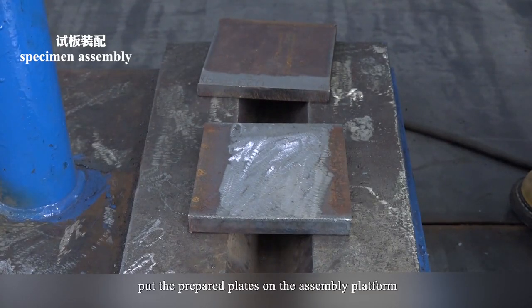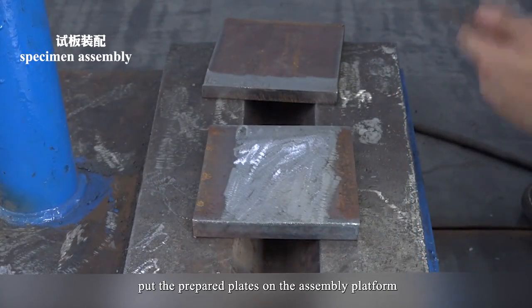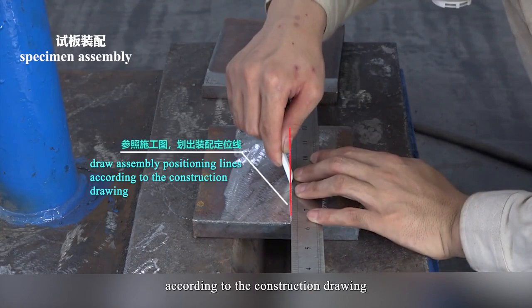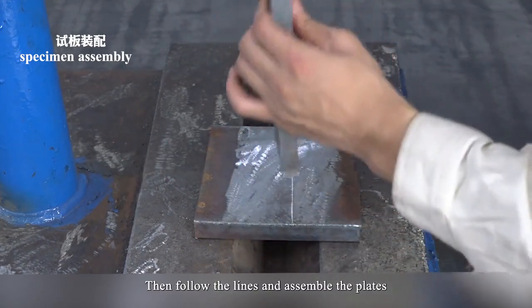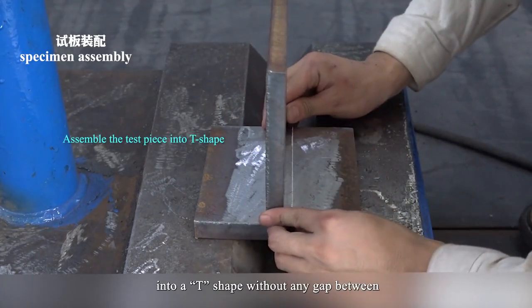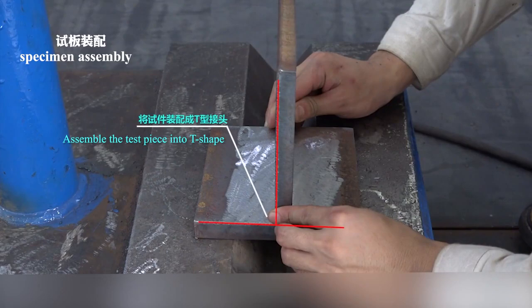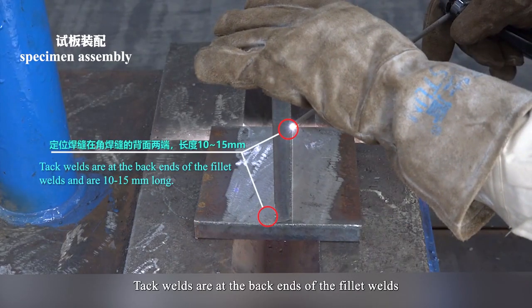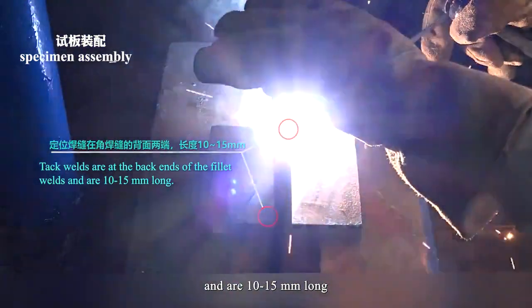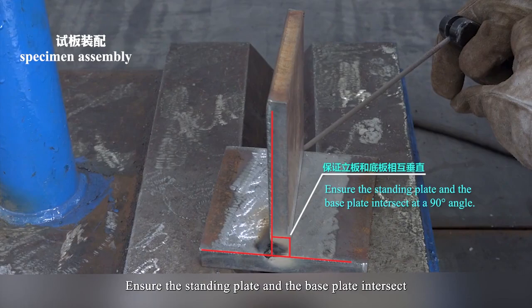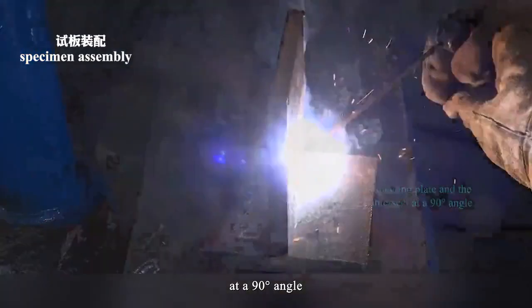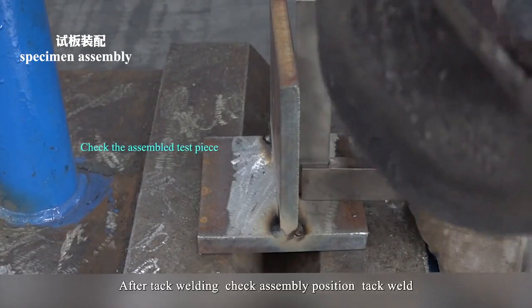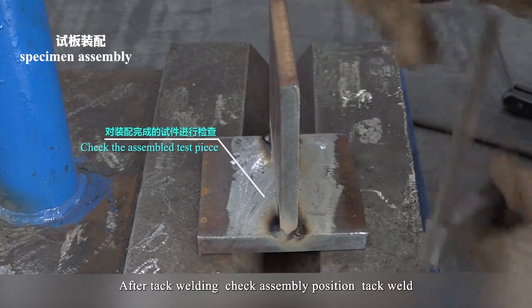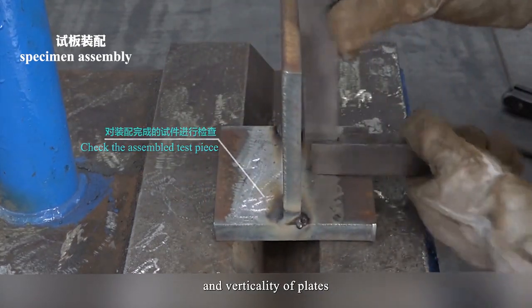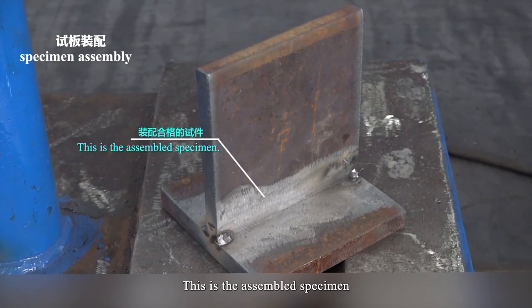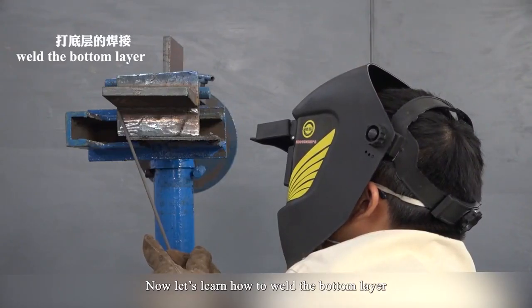First, pairing. Put the prepared plates on the assembling platform and draw assembling position lines according to the construction drawing. Then follow the lines and assemble the plates into a T shape without any gap between. Tack welds are at the back ends of the fillet welds and are 10 to 15 mm long. Ensure the standing plate and the base plate intersect at a 90-degree angle. After tack welding, check assembly position, tack weld and verticality of plates. This is the assembled specimen. Now, let's learn how to weld the bottom layer.